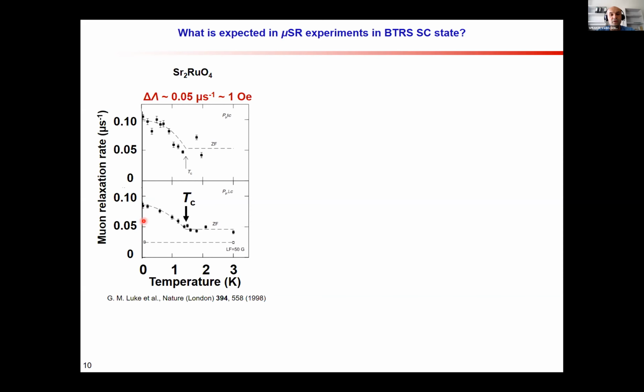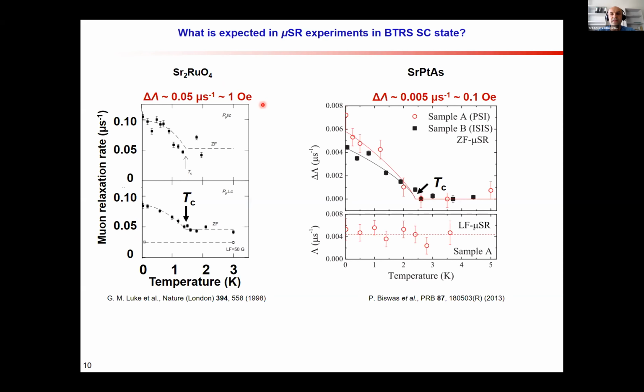Average value of these fields, for this particular case, was estimated on the order of 1 Ørsted. So these fields can be even smaller. For example, some other example like strontium platinum arsenide has a similar behavior, where this relaxation rate is enhanced below TC, but the amplitude of this enhancement is only a fraction of an Ørsted. So we are really looking for very tiny internal fields.